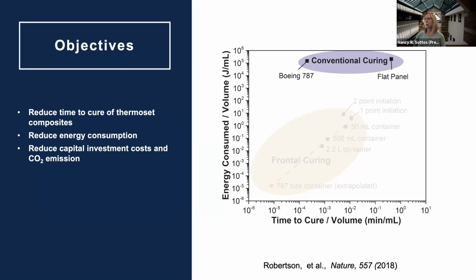I'm going to comment on some of the work that we published in 2018 on our technique, but this plot is taken from there, and I'll refer to it a second time in the talk. But let me just start out with conventional curing. As I said, it's pretty energy intensive, and we made this kind of Ashby plot of energy consumed per unit volume versus the time to cure per unit volume. And you can see whether you're making a flat panel or you're trying to make a 787 fuselage, there's quite a bit of energy per unit volume. And I said the energy does scale with volume for a typical autoclave process. And our goal, and I'll mention later on how, was to get more into this quadrant, reducing both time and energy.